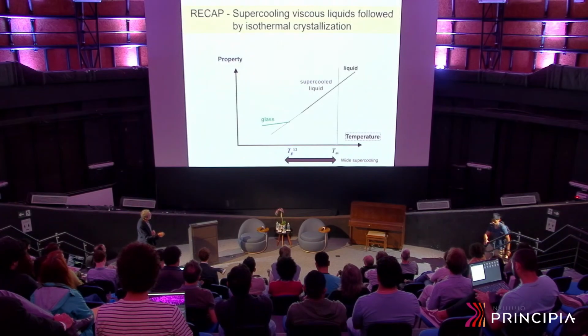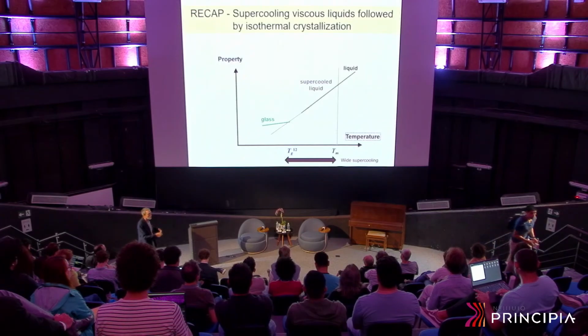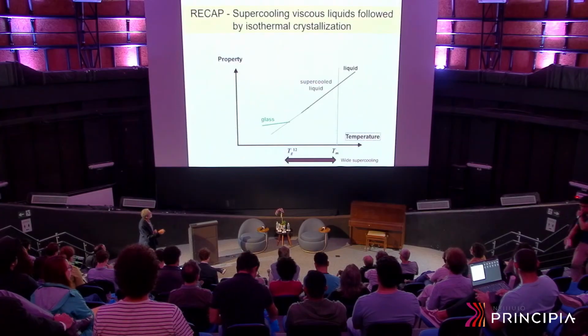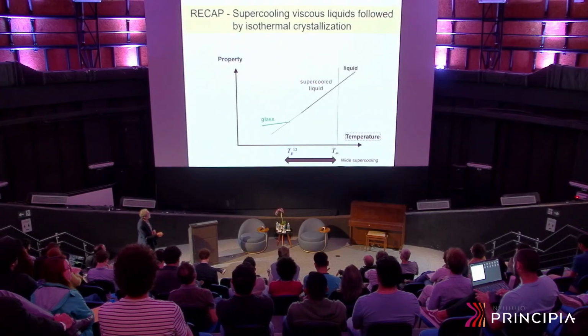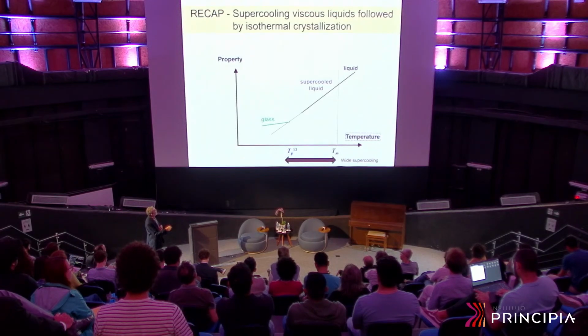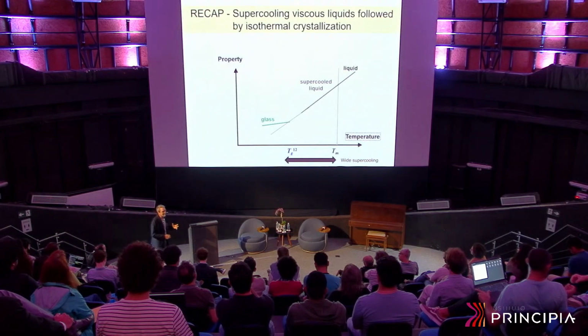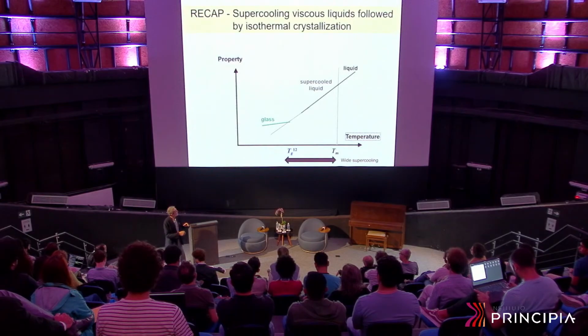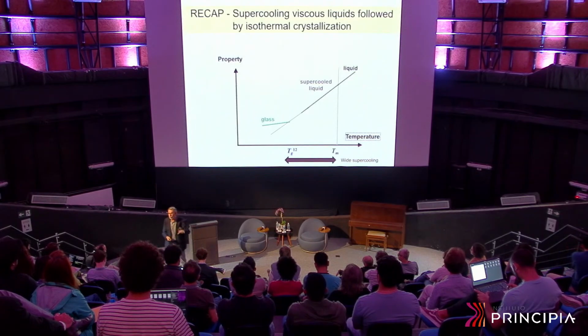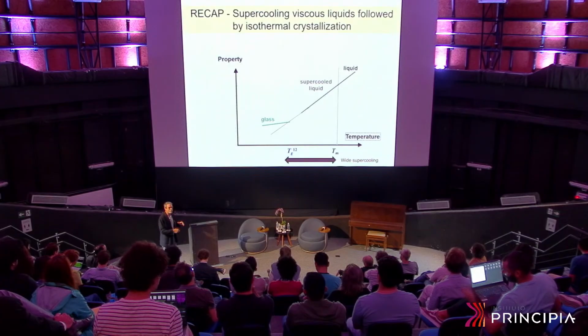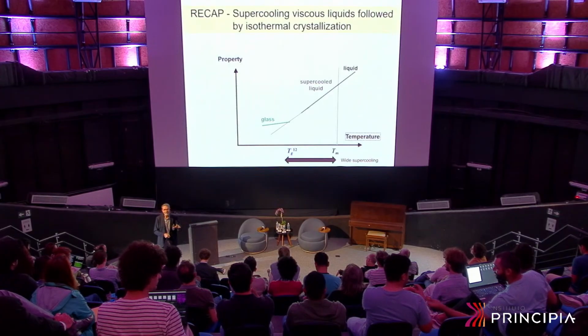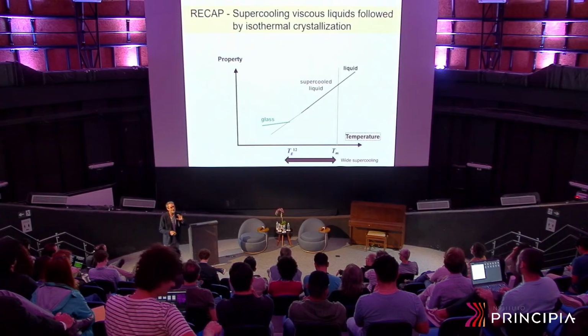And you keep coming down in temperature, and the viscosity increases and increases and increases. At a certain stage called the glass transition temperature, the material will become a rigid substance that we call glass. So glasses are defined only below the glass transition temperature. And they're rigid. They will break. They will shatter. They are rigid materials. But their structure is exactly the same as the supercooled liquid. So glasses are frozen liquids without crystallizing. Temporarily frozen liquids. They're not forever.